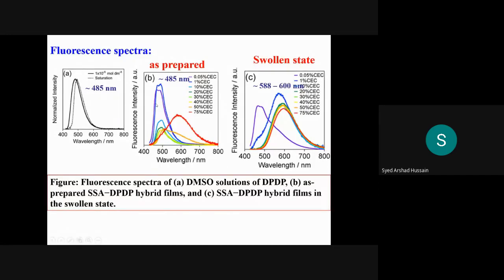An excimer is some kind of aggregation, and when an excited state molecule comes within the order of, say, 0.35 nanometers of a ground state molecule, then an excimer forms. And the excimer is an excited state phenomenon because you need an excited state molecule.